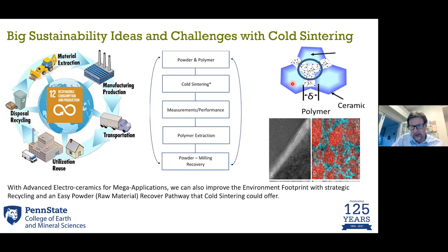rare earths. They may have very expensive levels of purity to those powders, and you could take those, mill them down again, and then re-drive this into a reuse cycle. Because again, after some milling, you could add it with the polymer, drive the cold sintering, make your devices again. And we've started to do some of these types of demonstrations with some of the mega applications that obviously are there with electroceramics, such as some of the batteries.